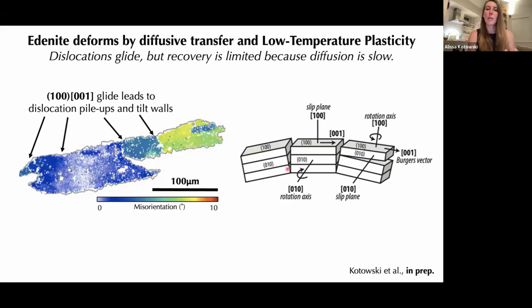So on this little block diagram on the right, that's basically shown by this middle block here, where you have dislocations gliding in this 100 plane at the top of this block towards the 001, the shortest Burgers vector, the easiest slip direction for a dislocation to move. And so what we actually can see is these dislocations gliding through and then creating these subgrain walls. This is where the dislocations are essentially piling up and getting stuck.